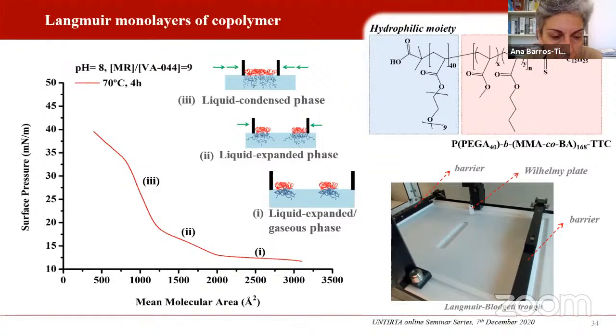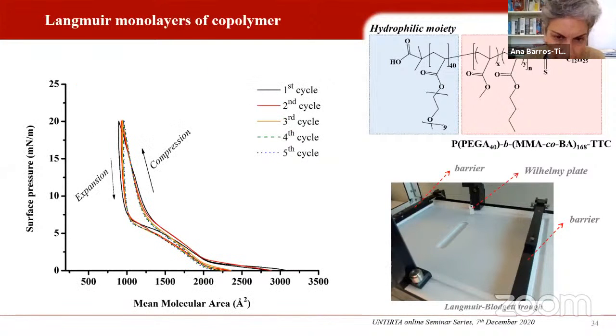So we can go through different organization levels. When the barriers are completely open, we have the so-called gaseous phase. As you compress the monolayer, it goes into a liquid expanded phase. And finally, when the area available is minimal, you have a so-called liquid condensed phase. So in that stage, we can inject the analyte, in this case avidin, into the subphase and see what the result is. And in fact, this is just to show you the monolayers were stable, so we could expand, close the barriers and open, and the result was okay. So the monolayer was stable.